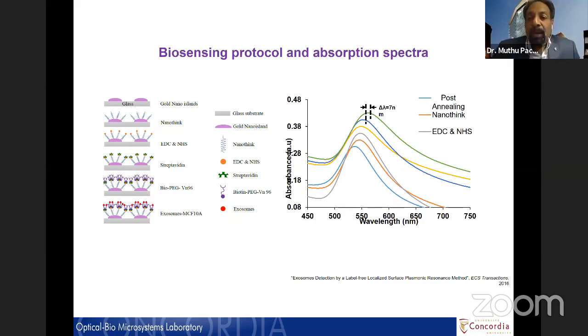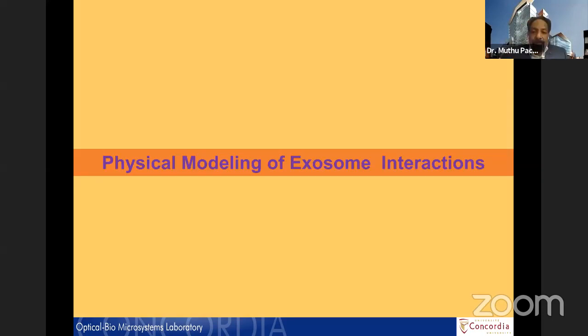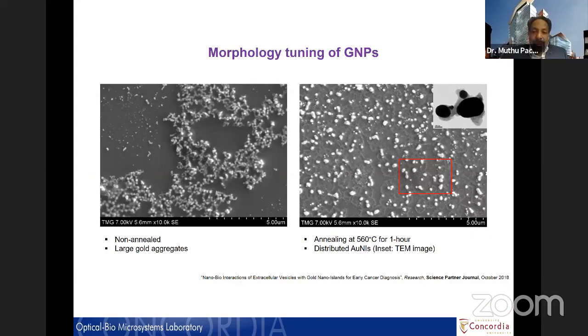Here we saw the delta lambda, which is the plasmonic shift, on the order of 7 nanometers, which seems to be high for us. Once we calibrate this plasmonic shift in terms of the concentrations, we can also get various stages of cancer in this case. We did some physical modeling of this too. So we can see some of this morphology tuning of gold nanoparticles.